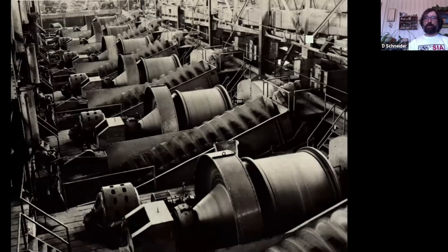The reclaimed sand got pumped into Calumet and Hecla regrinding mill number two. The mills you see are called ball mills — I believe these are Hardinge, but they might be Allis-Chalmers. They spun at a good rate of speed, full of hardened steel balls. When stamp sand passed through them, those balls pulverized the sand down to a very fine consistency, something like flour, enabling the use of newer technologies such as flotation to separate really fine particles of copper. They were able to operate profitably on what had formerly been discarded as a waste product — a very interesting aspect of copper processing history in the Keweenaw Peninsula.